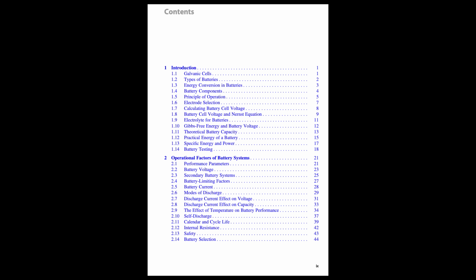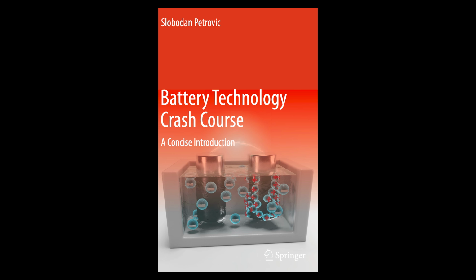Okay. What about just letting a battery sit on the shelf? They lose charge, right? Self-discharge. Exactly. Self-discharge. It's a slow, internal chemical process that consumes the stored charge even when the battery isn't connected to anything. How bad is it? It varies a lot by chemistry. Figure 2.17 shows lithium-ion is generally very good, low self-discharge. That's a big plus. Nickel-cadmium, on the other hand, tends to be much higher. Figure 2.18 shows the capacity loss over time. Could you get that lost charge back? Usually, yes, you just recharge it.